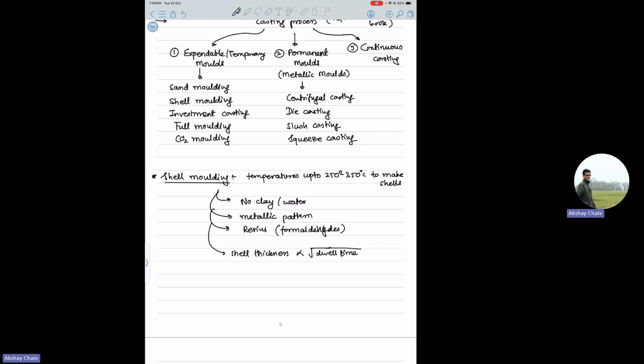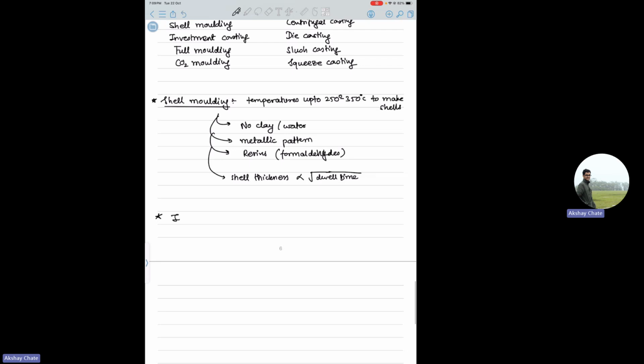Investment casting: in investment casting, they first make an assembly of your patterns. Then they dip that assembly in a slurry of silica flour, ethyl silicate, water, etc., so that your patterns are completely covered by a ceramic coating slurry. These patterns are usually made of wax. So first you put slurry on these wax patterns, and then you melt the wax, because wax usually melts at 40-50 degrees Celsius. Then you remove that wax. So you have a hollow shell of ceramic slurry, and then you put liquid metal into it.